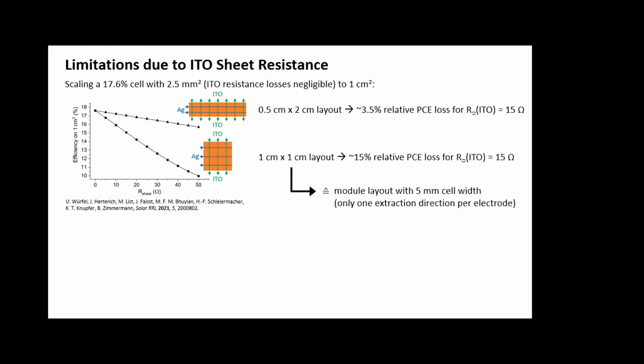And if you go to the module level, this becomes an even bigger problem, because for a cell, you can extract in 2 or 3 different directions with the bottom electrode, but for a module, you only have one direction, so this becomes an even bigger problem.